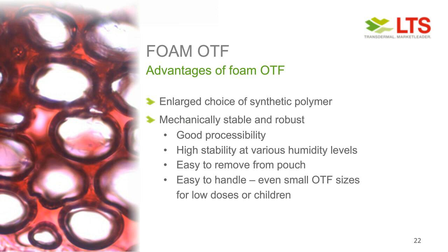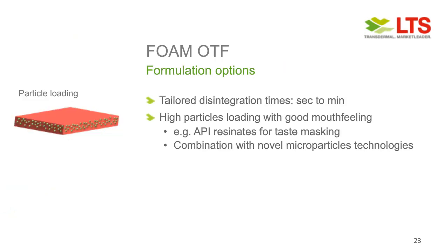Also in terms of sizing, since it's a bit thicker than a normal just 100 micron thin film, it's easier to handle. So even small sizes for low doses or for children are easier to achieve. Due to this foam structure, we have the opportunity to tailor the properties of the film very nicely. We can have fast disintegration times, like the flash wafers I mentioned before, within the range of seconds. But we can also create Meltaway films, which disintegrate within minutes or several minutes or longer, by the design of the foam or the thickness of the foam and the use of the polymers, of course.